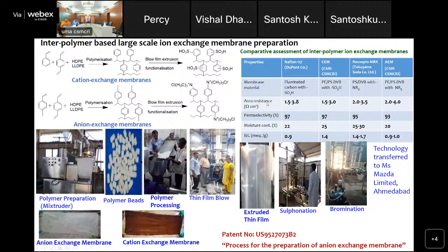The physical properties such as water uptake, and electrical properties such as ion exchange capacity, areal resistance, and selectivity of these cation and anion exchange membranes have been determined and compared with commercial membranes, the Neosepta membranes from Tokuyama. Our properties are close to the commercial membranes. The technology for the membrane preparation has been transferred to Mazda Limited, Ahmedabad. This is patented, and Mazda will start manufacturing the membranes very soon.